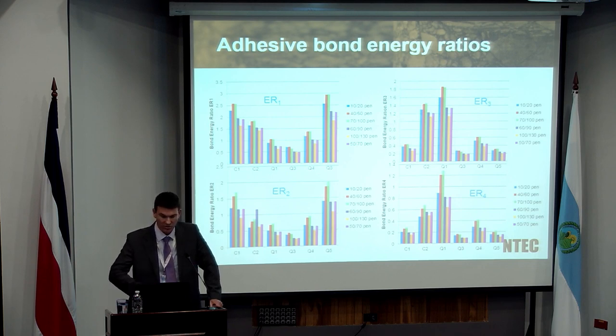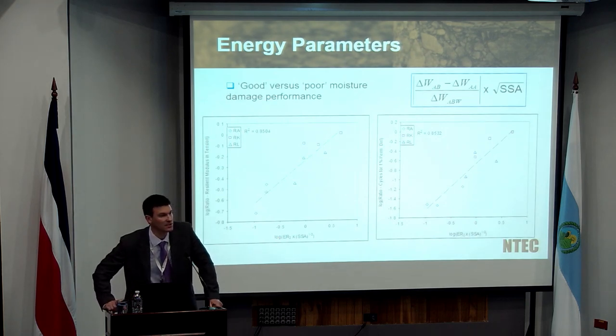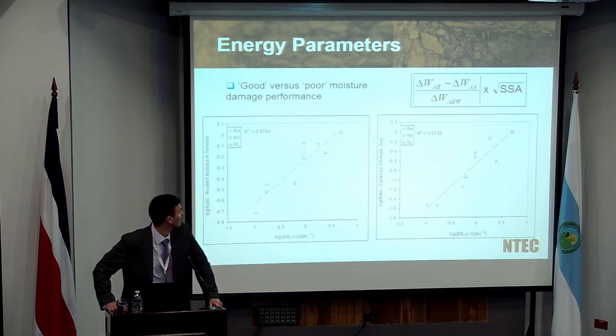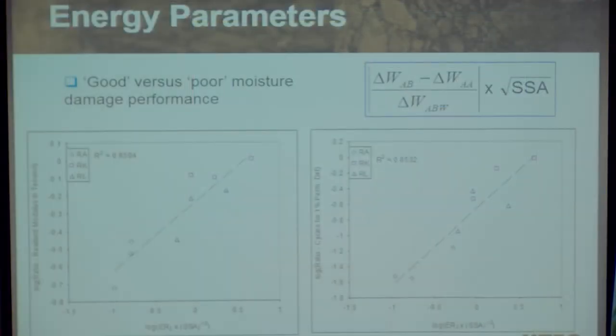Can we relate these two together? Well, yes, we can. So this is an example of some data using those surface energy parameters where we've got some indication of materials that are nominally good and materials that are nominally bad. And we've measured on the y-axis, the vertical axis, some measurement of the asphalt performance in terms of a wet-dry relationship. This is using some form of resilient modulus, so a modulus that was determined dry and wet, and its ratio, and relating that to this energy parameter.